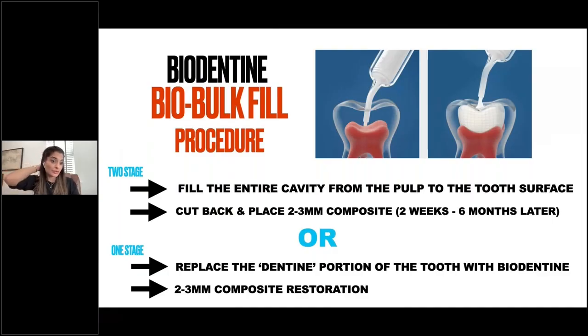So we can do this in 2 stages. I would say the two-stage procedure is the easiest way to use Biodentine. And if you don't mind treating that patient over 2 visits, then this is probably the easiest way to do it. So the first thing you do is fill the entire cavity from pulp to tooth surface with Biodentine, send the patient away after its 12-minute set, and then 2 weeks to 6 months later, they come back, you cut back the Biodentine and place a 2 to 3 millimeter composite layer on the top of it.